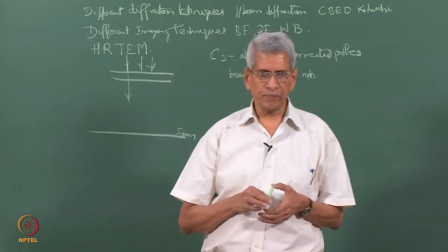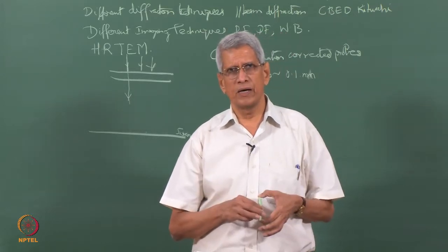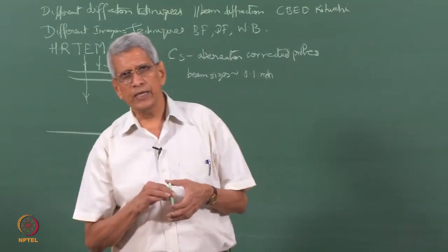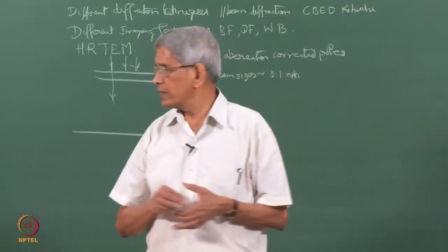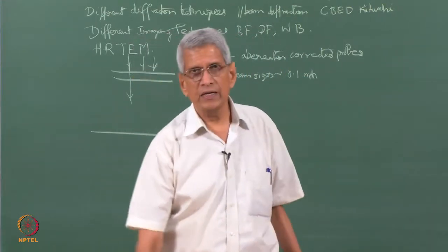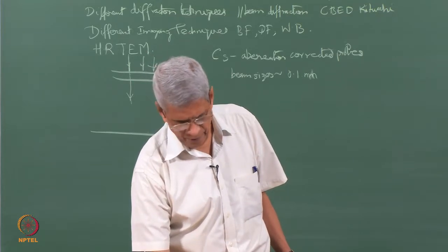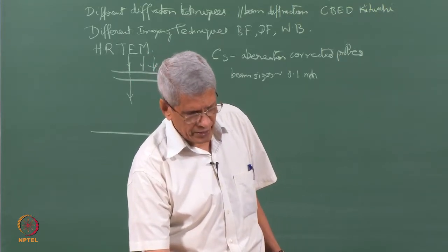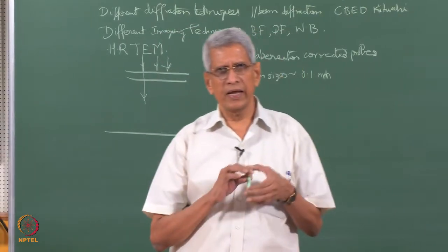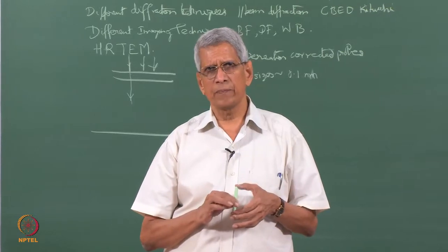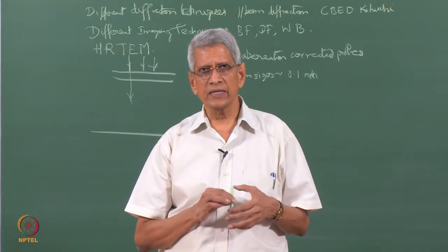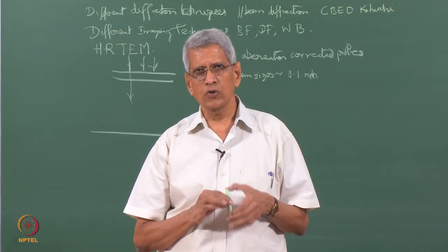Using this same facility in a scanning transmission electron microscope, using annular apertures, that is apertures which collect information at angles which are greater than maybe 3 degrees, one can get electrons which are essentially not Bragg scattering, it is essentially Rutherford scattering.